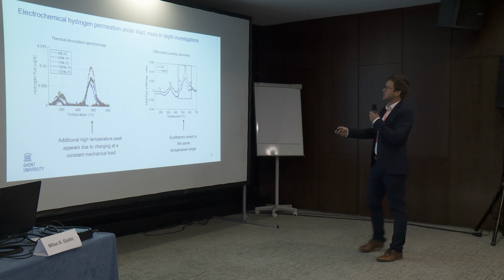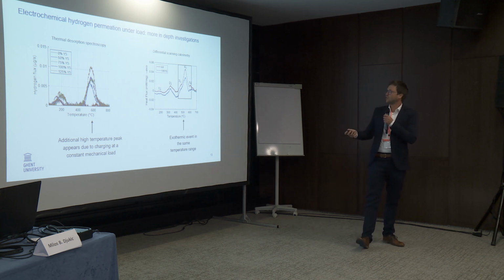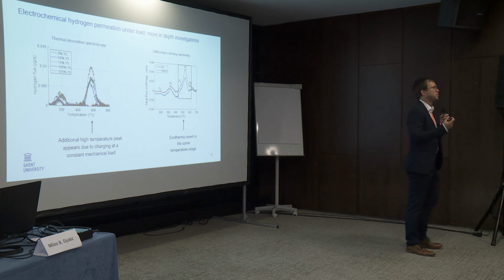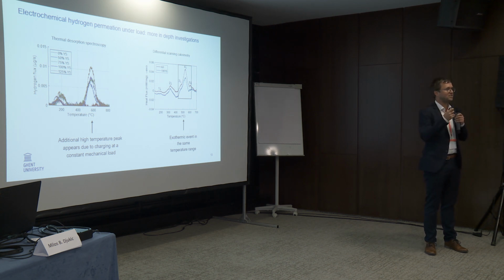And you have different regimes in this DSC measurement. The first one is basically clustering of carbon atoms at that temperature, which is a prerequisite for the precipitation of transition carbides that is then happening in phase 2. And then in phases 3 and 4, we have indeed the decomposition of austenite. So basically your retained austenite at these temperatures will decompose, and it will turn into BCC again.